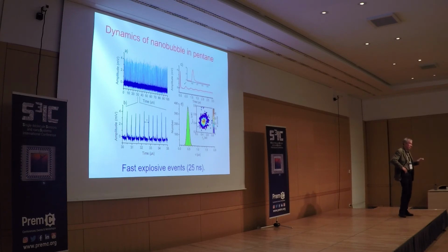It's just the same instability you can hear when you boil water for your tea. You hear the bubbles doing ding, ding, ding, ding, right? So this is basically the same phenomenon, but because our pan is so much smaller, typically sub-micron, the times are also much shorter. The lifetime of the bubble is typically a few tens of nanoseconds, and the duration between explosions is typically 500 nanoseconds, or half a microsecond.